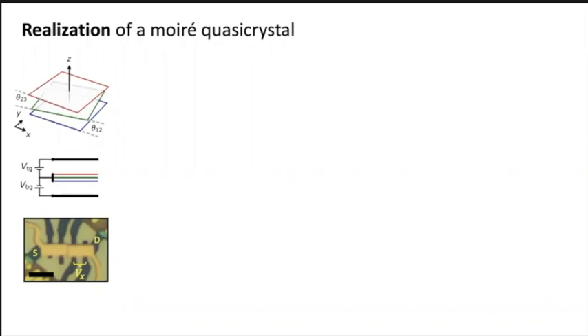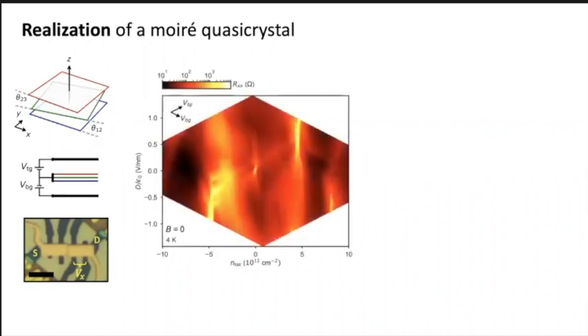And the structure has a bottom metallic plate and a top metallic plate with which this trilayer forms parallel plate capacitors, so that applying two voltages, we can control the density in the three layers and independently the electric field, the transverse electric field that can polarize your wave functions in the three layers. So if you measure the resistivity versus displacement field and total density, okay, you have a pattern like this.